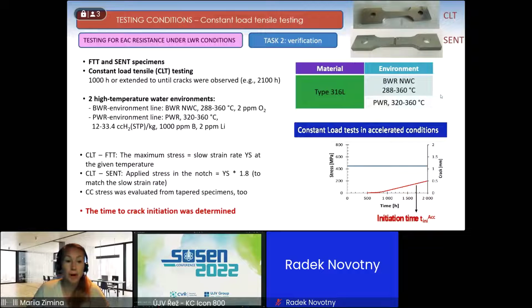In this part, we used both FTT and SENT specimen. We used constant load testing for thousands of hours, or some of the tests were further extended until cracks were observed, because we didn't observe cracks after thousands of hours in some cases. The same environments were chosen, BWR and PWR. Also, I probably need to mention why we used two environments, obviously because we wanted oxidizing and reducing conditions to be represented.